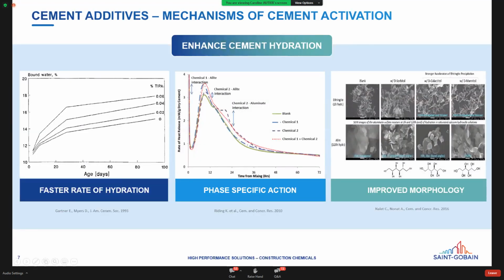Thank you, Pooja. The chemicals used in activators increase and accelerate the hydration of specific clinker and SCM phases. On the second picture, you can see examples of the influence of chemicals on the total heat flow released by a cement paste over the first hours of hydration. Chemical 1 significantly increases the main peak intensity linked to the silicate phase hydration, leading to the CSH precipitation. And on the other hand, chemical 2 mainly influences the second peak, corresponding to the sulfate depletion point, when the calcium aluminate hydration and ettringite precipitation are faster.